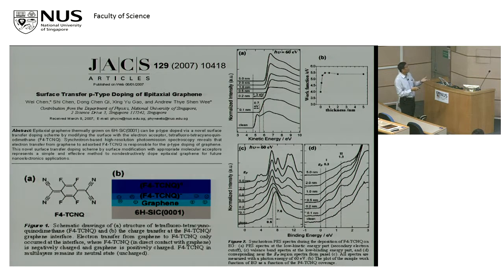And we showed charge transfers through work function changes and so on. So a very simple experiment, the sort that we have been doing all along, just change the substrate. But it turned out to be the first paper of molecular doping of graphene. And because, if anything in a scientific field is first, it gets cited quite well. So this paper is pretty well cited.